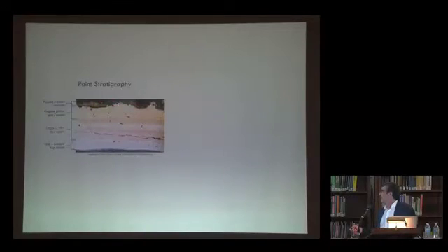There's a primer that was applied. This is the original cocoon. You can see it's a high, thick build, elastomeric coating, and it was very unusual for its day in 1959. And that was applied, as I said, in 1959. This set of layers, we think, were applied between 1960 and 1991, and we do know that this layer here was applied during the 1992 restoration when the addition was added.